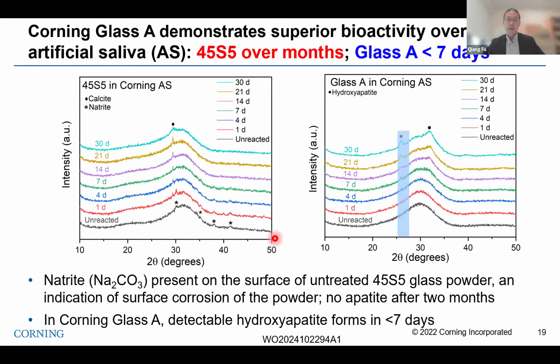In one lab study, we took 45S5 and our glass composition in artificial saliva. This picture shows how the crystalline phase changes in 45S5 and our composition after 30 days. What you notice is for 45S5, we only saw some calcite or natrite formation after 1 month. We even did the experiment up to 2 months, and we still did not see any apatite formation. As you all know, apatite formation is a key criterion to evaluate the bioactivity of any material.